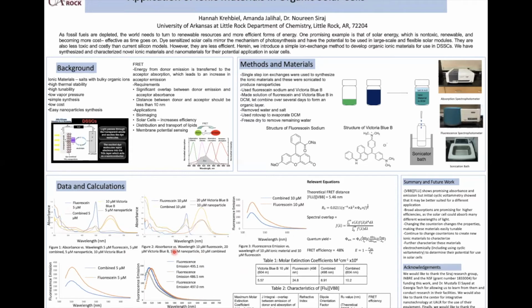In order to determine if our material was indeed exhibiting FRET, we conducted some of these calculations here. We have our maximum molar extinction coefficient, which we obtained from our absorbance graphs. Here we have our calculation of J integral, which is the overlap between emission of the donor and absorbance of the acceptor. We see that that's to the 15th power, which is a high number. It's a good indicator that FRET is occurring. And our theoretical FRET distance was within 10 nanometers. We calculated it to be 5.46. So that shows that FRET could indeed be occurring.